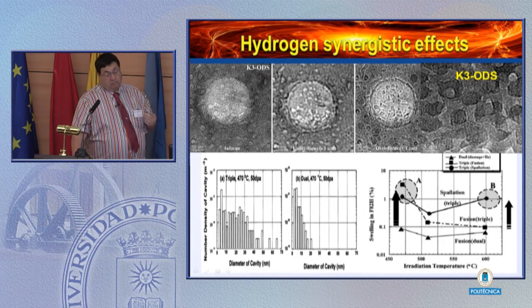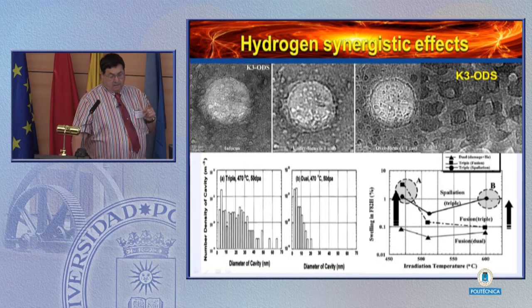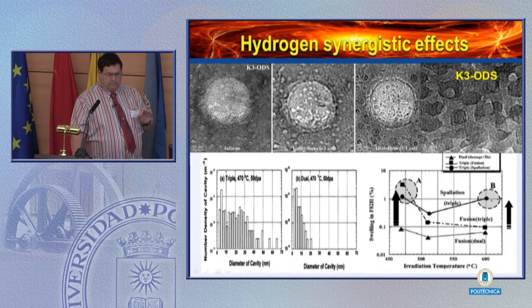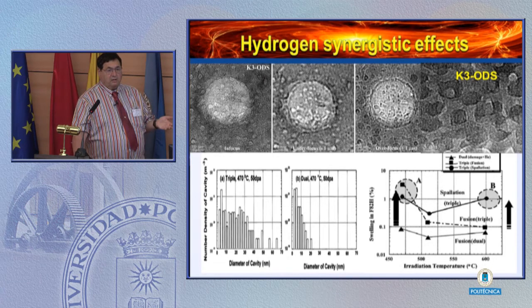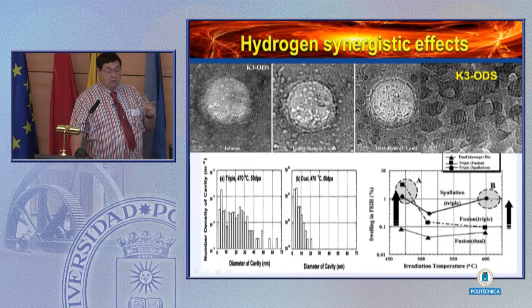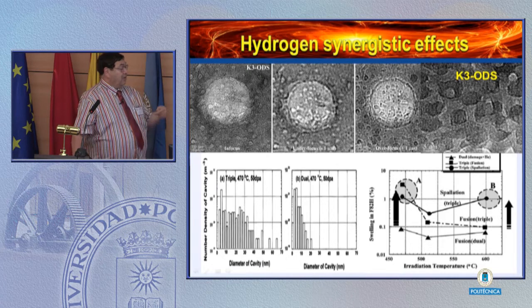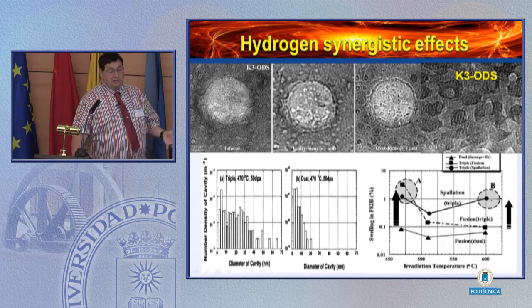This had been discovered in reactor-irradiated ODS materials, that there's a halo effect formed. If you irradiate at intermediate temperatures, and then quench the specimen, you discover that the ODS particle has a halo around it. And what this halo appears to be due to is ballistic collisions that have decomposed the yttrium oxide, creating free oxygen, which then, if the temperature is high enough, recrystallizes over a period of time and can be made to disappear. But what this implies then is during the irradiation period, there's free oxygen in the system. Just like there's a steady state population of vacancies and interstitials during irradiation. Remember, radiation damage is a non-equilibrium process. And so there's a lot of things going on.